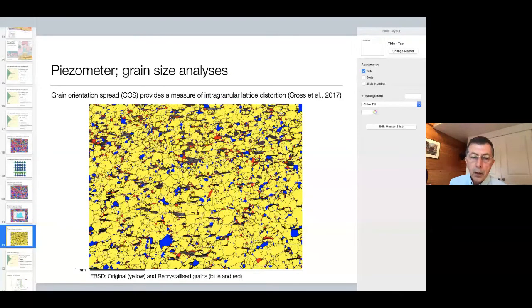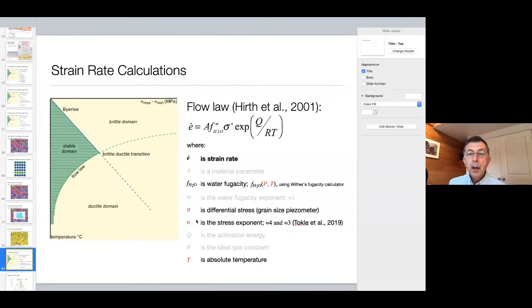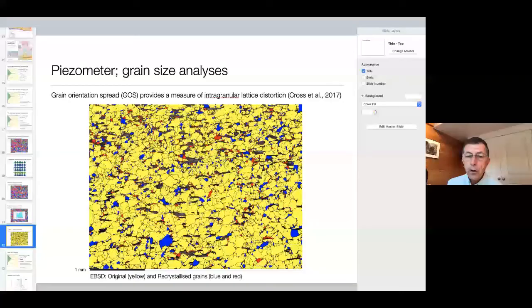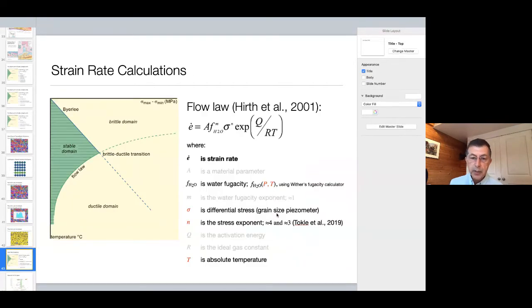So when we determine the grain sizes, we can use them as a piezometer to calculate the stresses. So for each sample, we calculate the grain size and from that the differential or flow stress according to this equation. As I showed you in the previous diagram, there are also two generations of quartz grains, the original, larger ones and the smaller ones. So we did this exercise, this measurement, for all grain sizes.